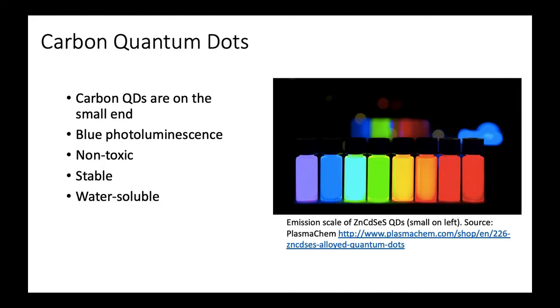Carbon quantum dots self-dope, meaning that their optical and electrical properties are tuned for blue photoluminescence, as they are around 2 to 3 nanometers. Doping describes how impurities and defects alter optoelectric properties. Using another compound, such as cadmium selenide, which is toxic, can result in quantum dots that are different sizes and emit other colors of light.